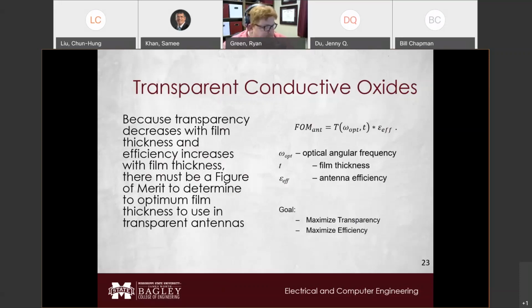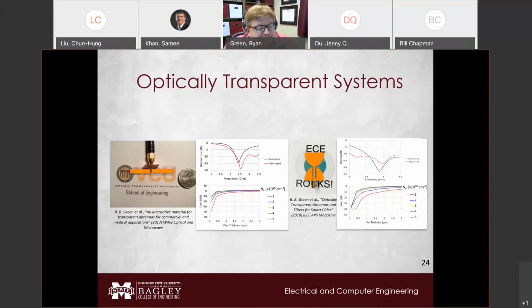So if we do that, we can apply this to independent, different designs. Here are two designs that I made. One is a planar dipole, and the other one is a coplanar hourglass antenna. That's the general shape, but they're actually just transparent in and of themselves. And we find that we have a resonance shift in our antenna from a design of 2.4 gigahertz to about 2.5 with the dipole, as well as lower gains than expected. At 1.5 micrometers thick, we actually got a gain of about -3, which is substantially lower compared to the gain that we normally expect, which is about +2, by the way.